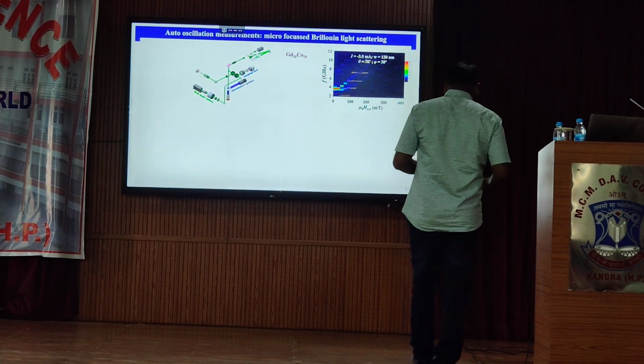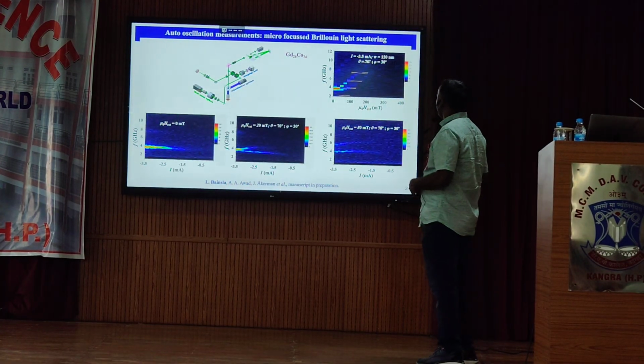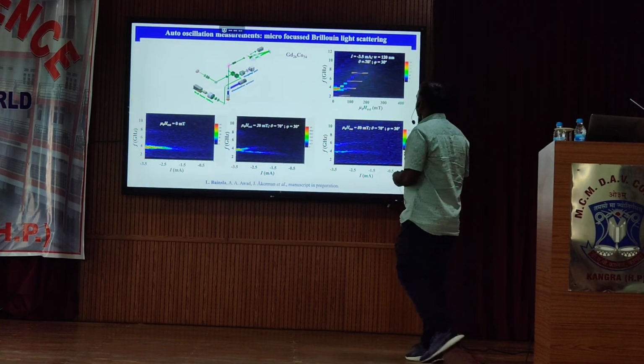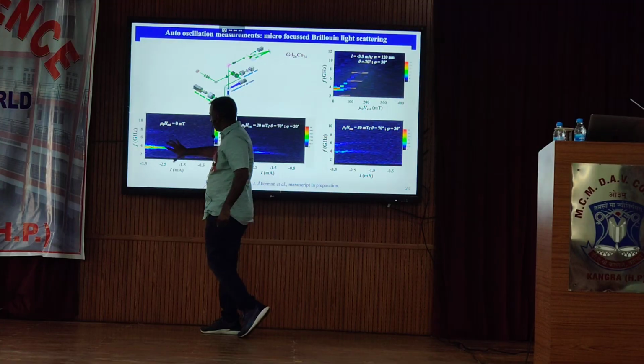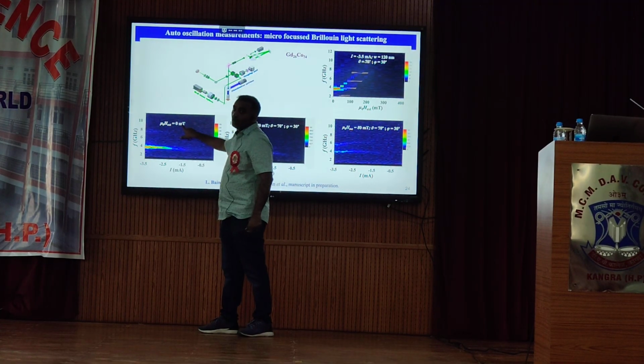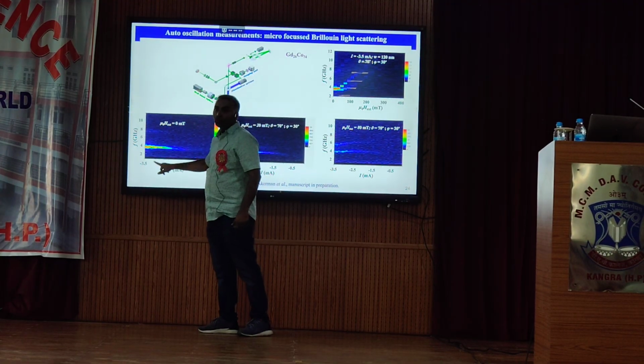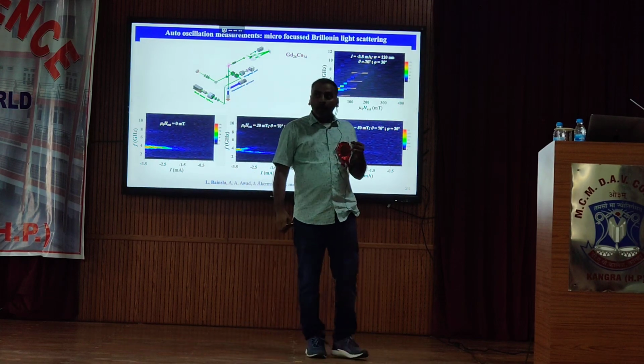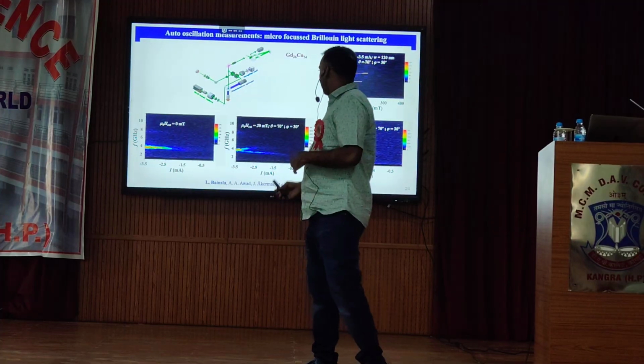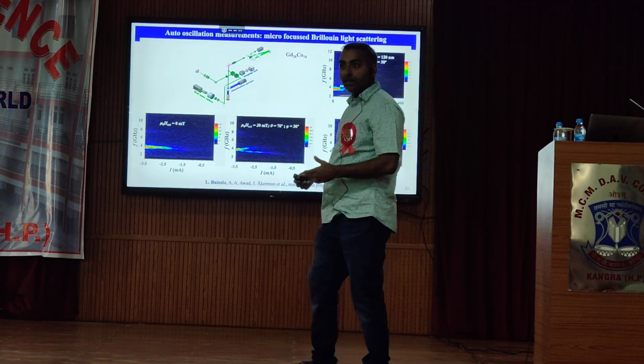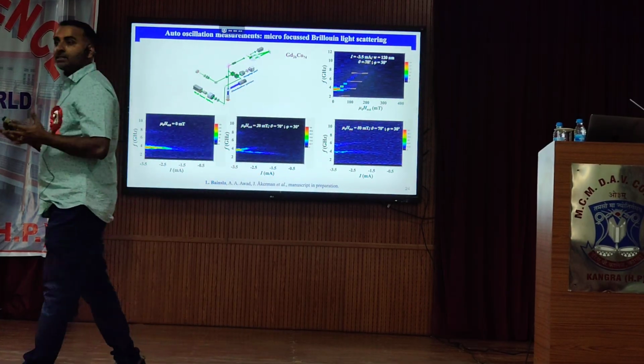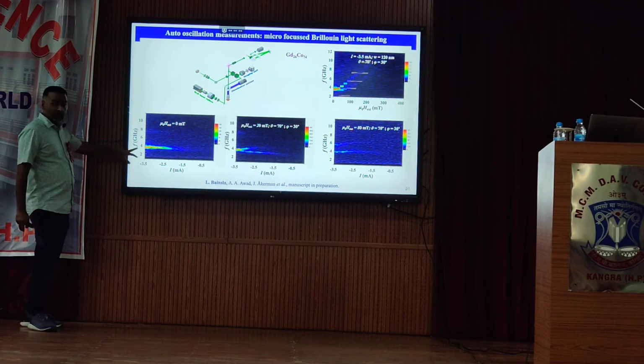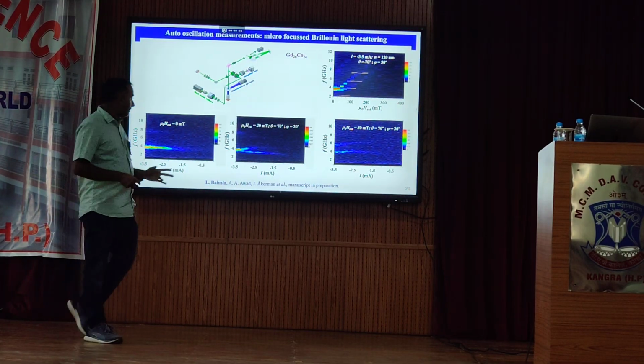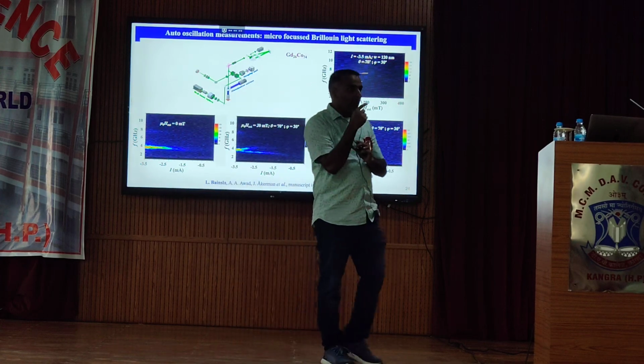So then we again use the laser-based setup to measure the magnetization oscillations. And with this setup, we also got the magnetization oscillations for this sample. But the interesting thing comes here in this image. As you see here, the applied magnetic field is 0. We are not applying any magnetic field. Rather, we can see the magnetization oscillations. So this was the first time, to the best of our knowledge, that it is reported that magnetization oscillations can be achieved without any magnetic field. Usually it is required to supply a magnetic field to the sample to get the magnetization oscillation. But in our sample, since these are different materials, compensated ferrimagnets, we were able to get zero field magnetization oscillations. We only applied the charge current. We did not apply any magnetic field, but still we can see our magnetization precessing very steadily.